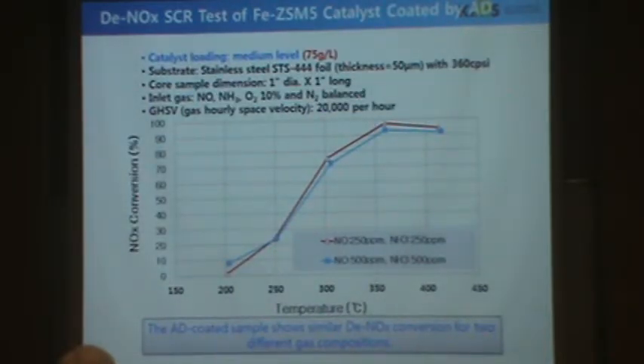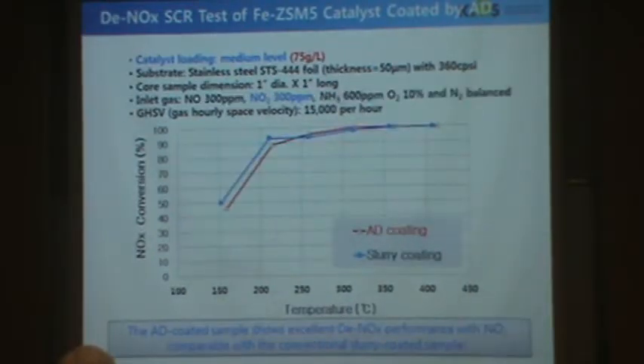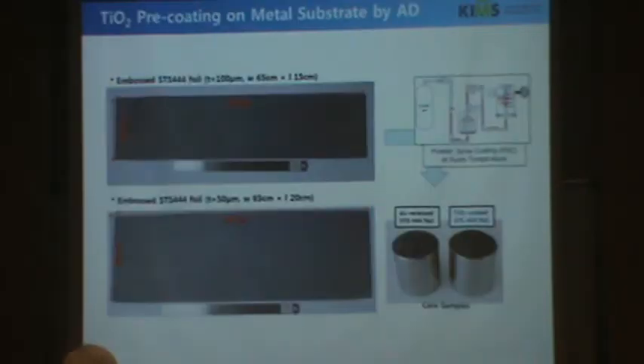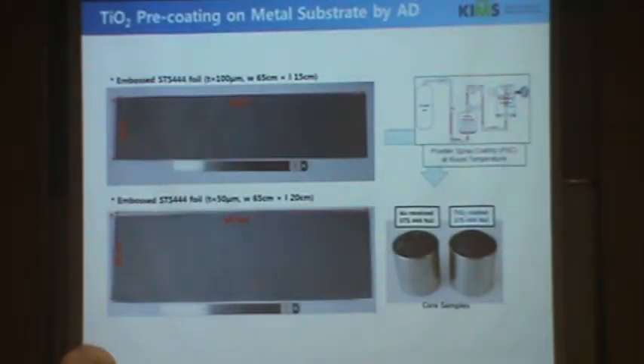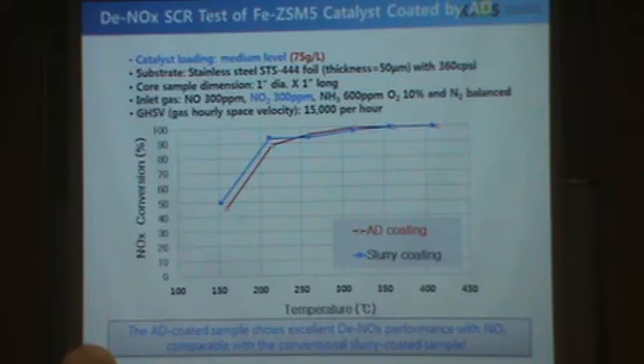And we changed the concentration of NO from 250 to 500. And we added some NO2 to check the effect of NO2. So we got very, very good performance, even though we did not optimize the catalyst samples. So for every sample we can obtain similar performance. So that was our goal. And then actually, with the previous samples, I don't think that we can commercialize this technology to apply to a real system.